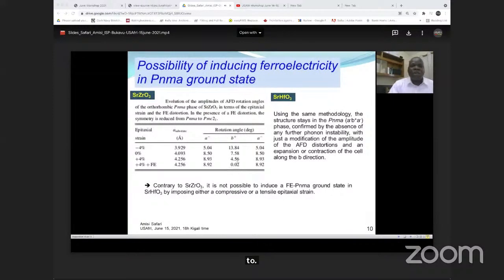To see the possibility of inducing ferroelectricity in the Pnma ground state in both compounds: for strontium zirconate, we succeeded in inducing ferroelectricity in the Pnma ground state, so we get Pmc21. But strontium hafnate prefers to stay in the Pnma phase. Contrary to strontium zirconate, it is not possible to induce a ferroelectric Pnma ground state in this compound.